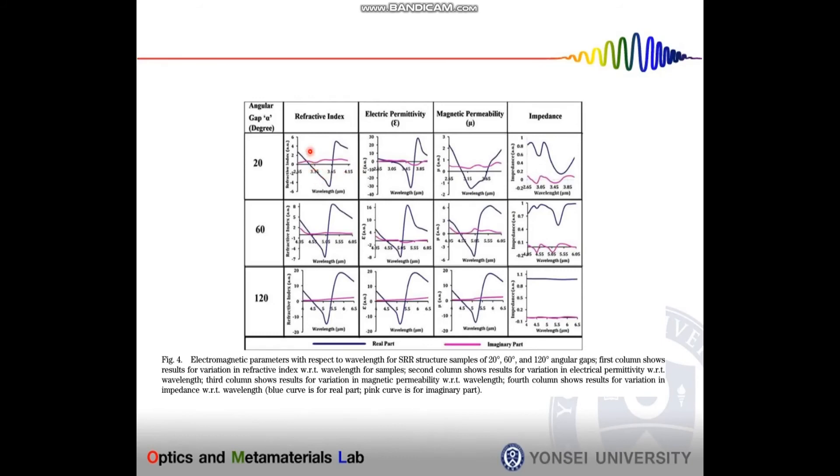We further calculated the refractive index of the corresponding structure and it is showing real negative value at the resonance wavelength. The electric permittivity and the permeability also show real negative value at the same resonance wavelength.